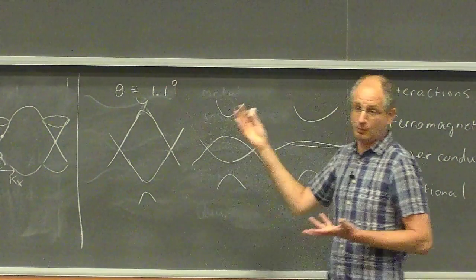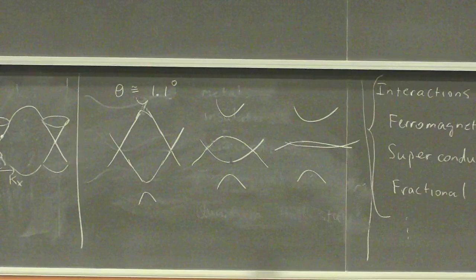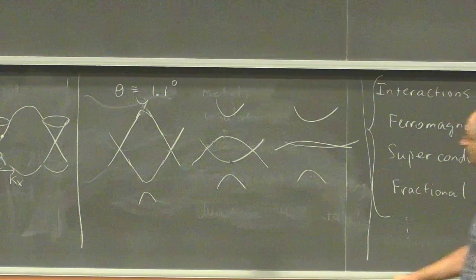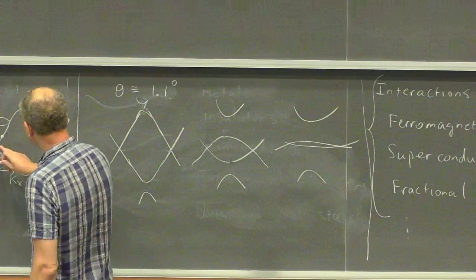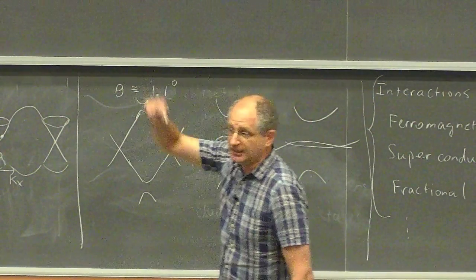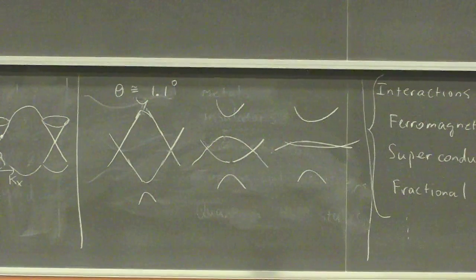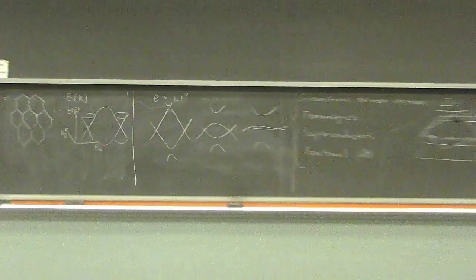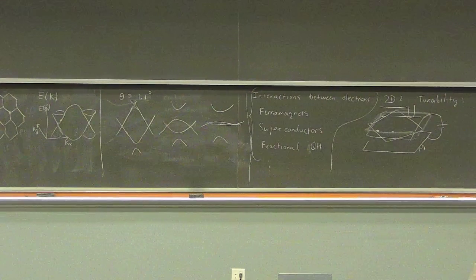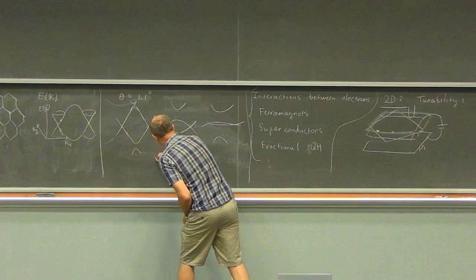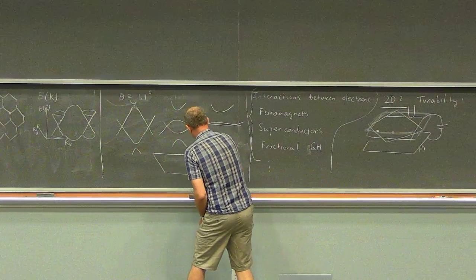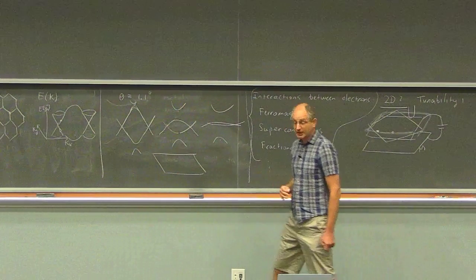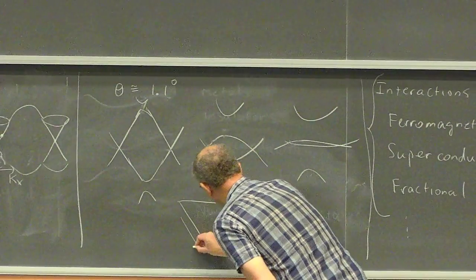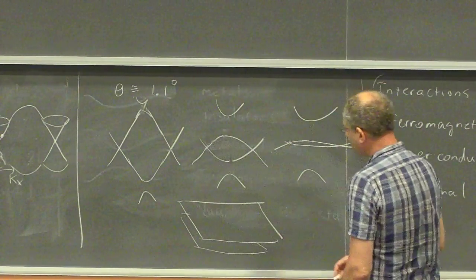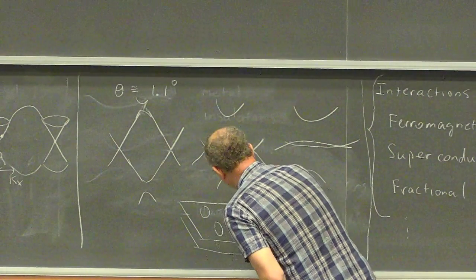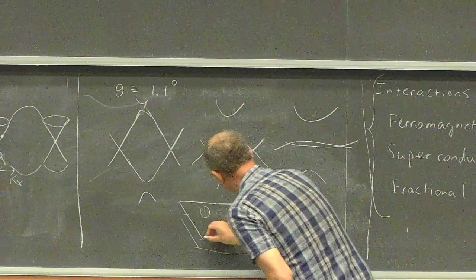So what actually sets this magic value of the angle? Where does this number 1.1 come from? It turns out that number comes from the ratio between the strength of the tunneling between the two layers and the speed of electrons within each layer. In fact, this is an interference phenomenon. Just to understand where the number comes from, you can think about it very simply. You have your two layers. They form this large-scale Moiré lattice.